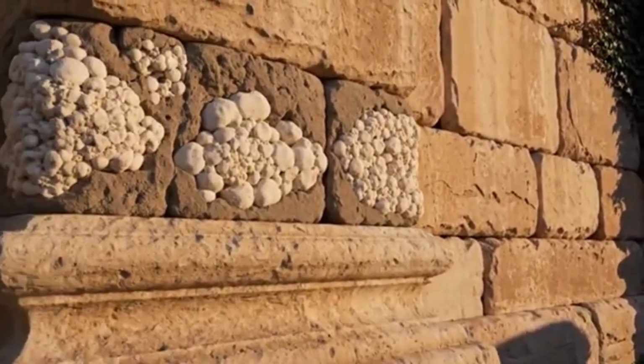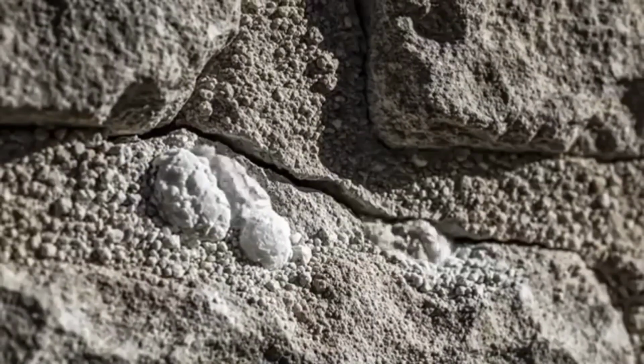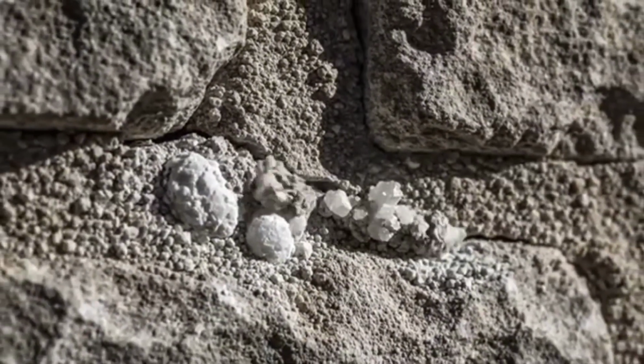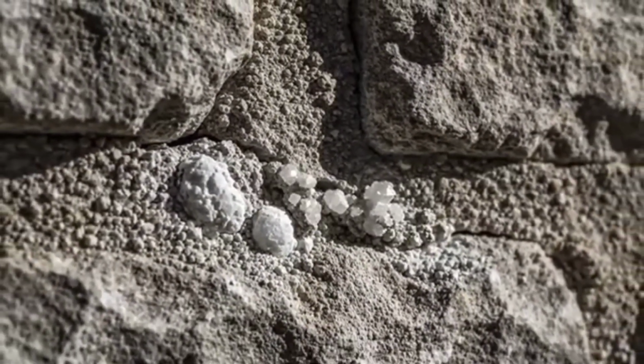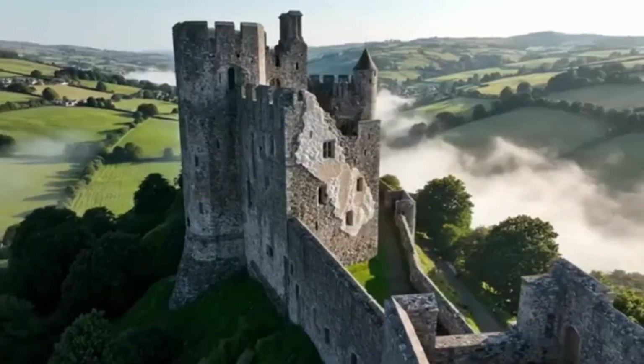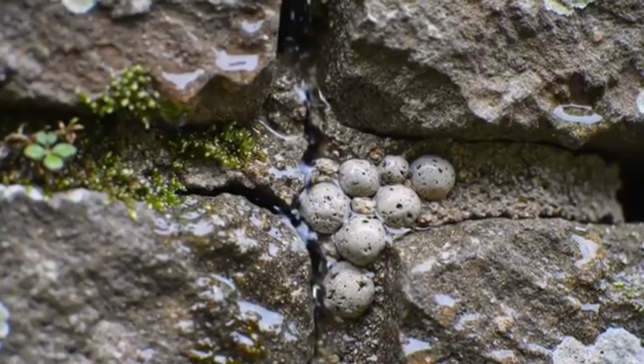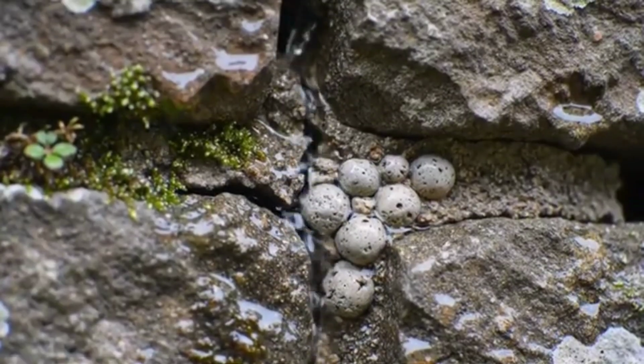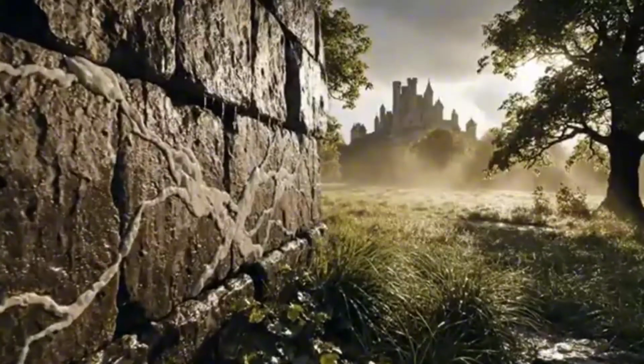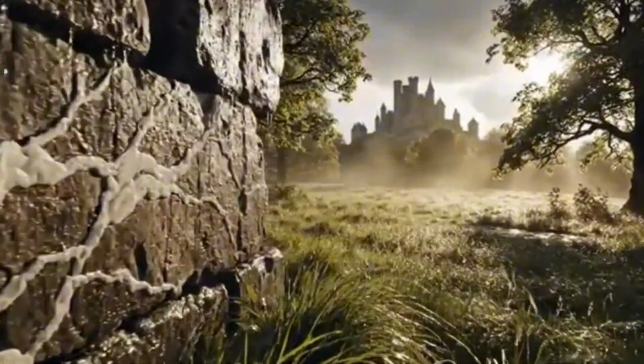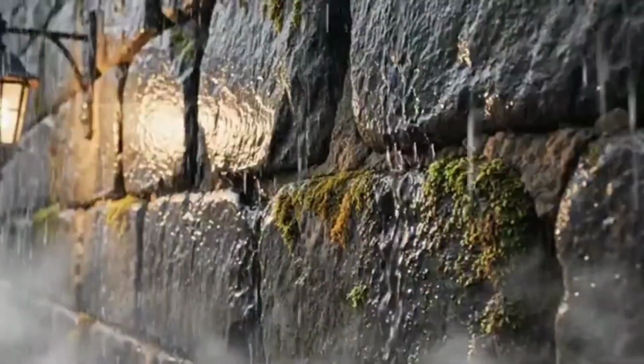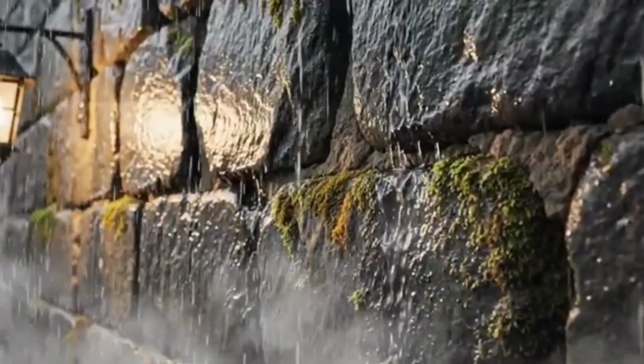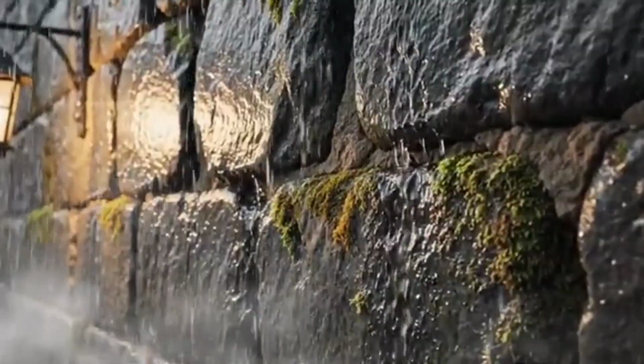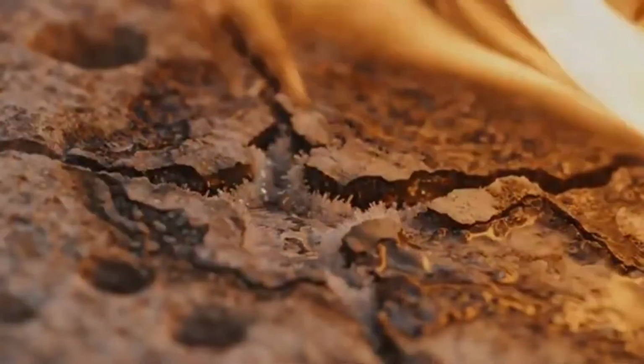An identical batch made the modern way with slaked lime never healed. After 30 days, no change. The water kept flowing through indefinitely. Every lime clast distributed throughout Roman concrete is a dormant reservoir of reactive calcium. When activated by water entering a crack, it restarts the cementing process locally, exactly where the damage occurred. The concrete doesn't just survive damage, it responds to it.